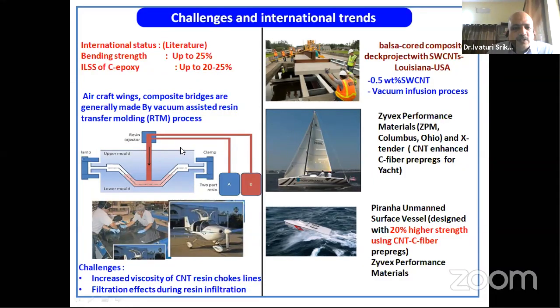As I told, resin transfer molding is one of the processes used for large structures like aircraft wings. And I told that the fabric layers act as filters for the CNTs. So you cannot use this process. So what people have done is they made prepregs. Prepregging is where you take the fabric, run it through a resin bath mixed with the CNTs, then dry it. That means some semi-curing, that is called B stage. So that is called a prepreg.